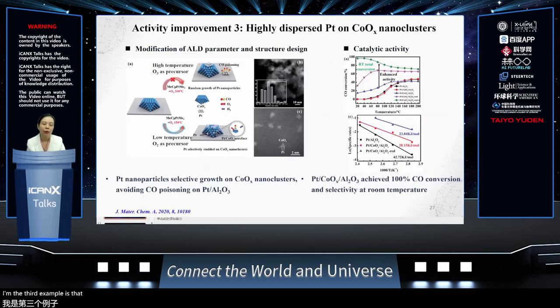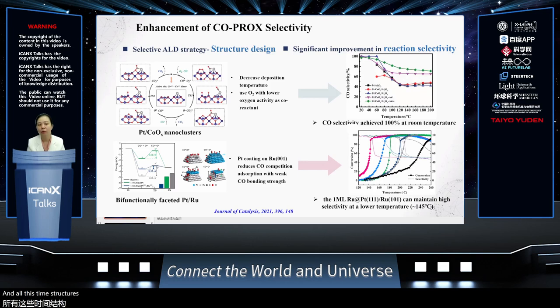The third example is that by utilizing a different co-reactant, we'll be able to lower the process temperature, and it helps us adsorb on certain facets, and we'll be able to obtain a kind of single atom catalysis. But if we do not run this kind of decreased temperature, if we run it at elevated ones, you actually get coatings and depositions all over the places. And all of this shows that for the selective process, you have temperature, partial pressure, and your chemistry. All of those can help you obtain the different kinds of structures that you want. And all of this will help you build up atomic scale nanostructures. And all these types of structures give you not only activity enhancement, but sometimes also selectivity enhancement as well.